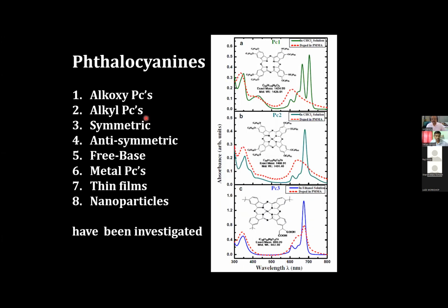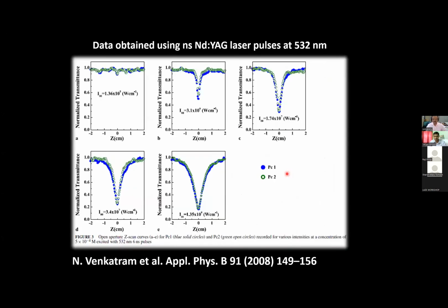So some materials, for example, you see this is one phthalocyanine with different peripheral groups with no metal inside. Then you have a zinc metal here, but with the same peripheral groups. So no metal and zinc. And in this case, there is a zinc metal, but the peripheral constituents are different. So when these things are designed and produced in the lab, you get different absorption properties and emission properties. So when you change absorption and emission properties, your nonlinear properties will change.